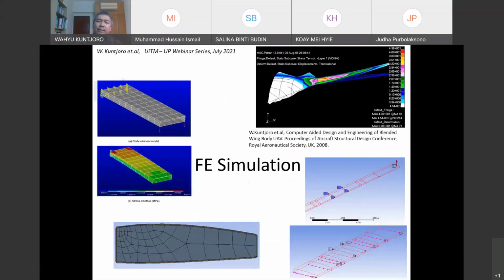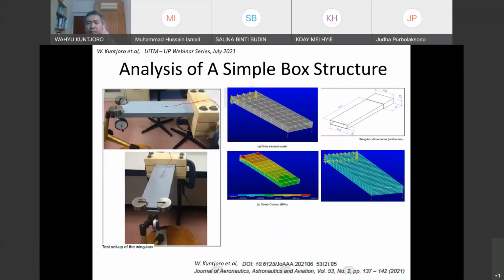Okay, so now let's go to what we have been doing in terms of FE simulation. Based on that, when we build FE simulation, of course we are going to make use of mechanical properties based on the way we print the component. So over here is basically what we did 2 years ago. We want to check whether the simulation we do is going to be validated by the testing. So we have a very simple test here, a hollow box, which is simulating the wing box, and the displacement measurement is very accurate, meaning that the simulation of displacement is basically the same as the test, but the stress has a 20 to 30% difference. That means we need to investigate the reason why we have such a big gap, 20-30% of stress at a certain point here, which we measure using a strain gauge.